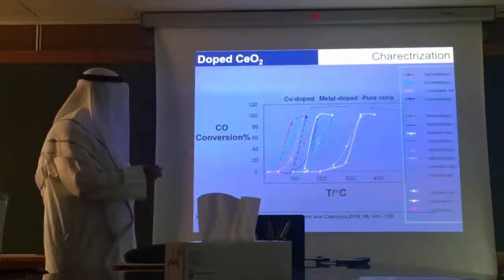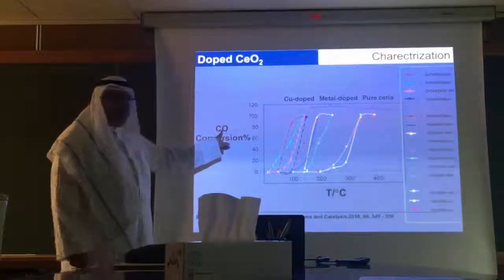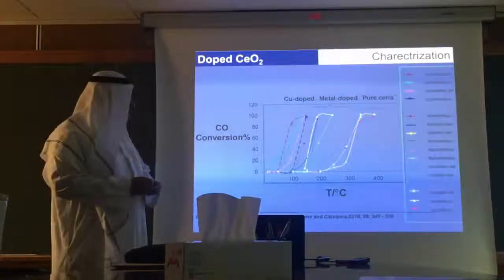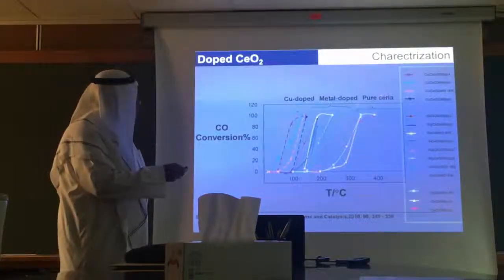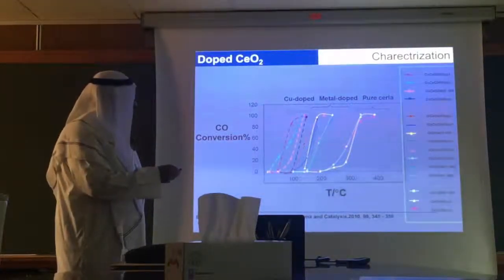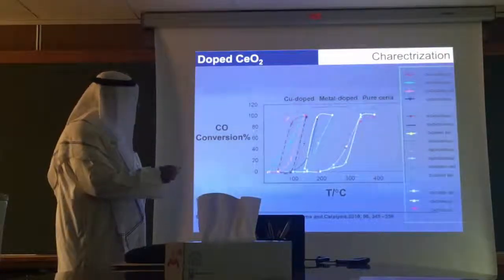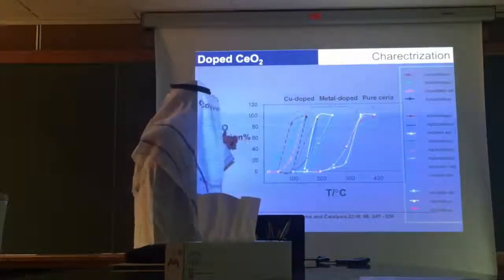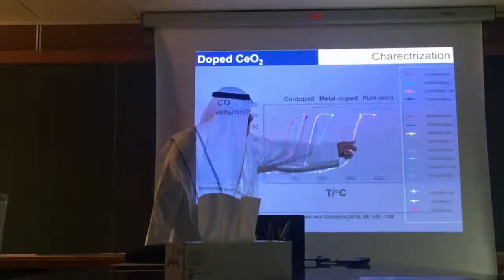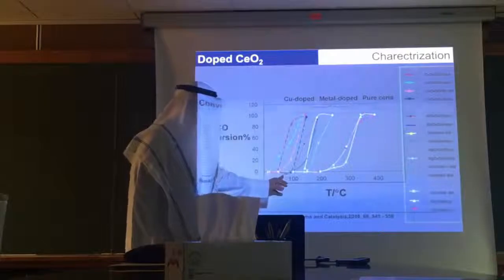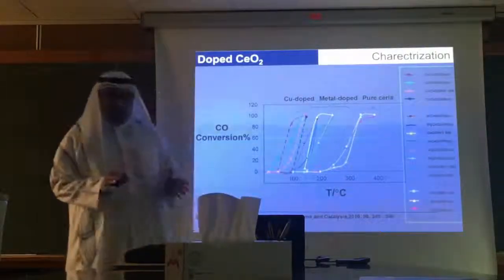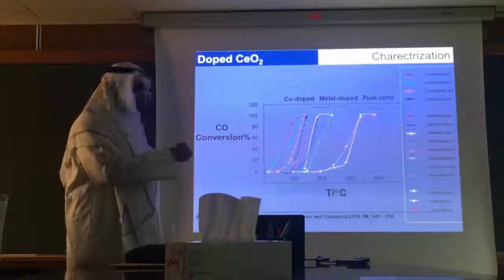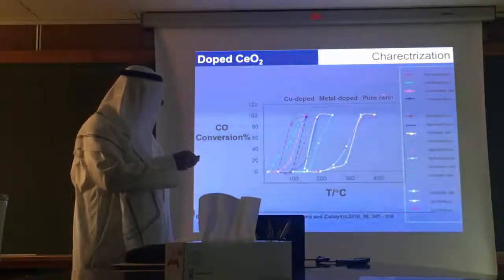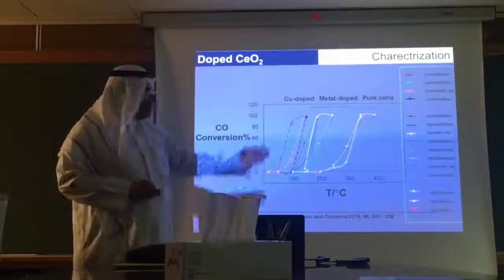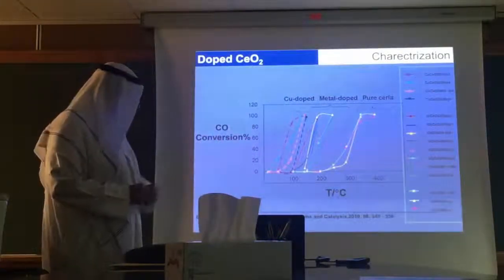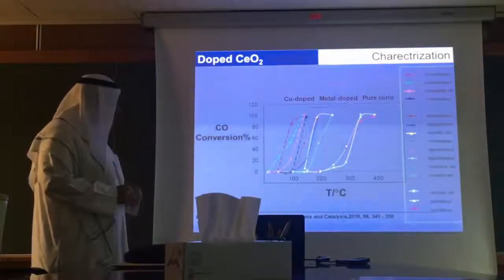This is the example. We tested first for the carbon monoxide, because if the catalyst is good for carbon monoxide conversion, it will be good for the NOxes. And we prepared pure cerium oxide and doped cerium oxide with different metals, and here I use copper. And copper actually shifts the carbon monoxide total oxidation from a temperature around 300 to a temperature less than 100. So we can convert the carbon monoxide to carbon dioxide at very low temperature just by doping the cerium oxide with a small amount of copper oxide. So we shifted a huge distance, and this work was published in several journals.